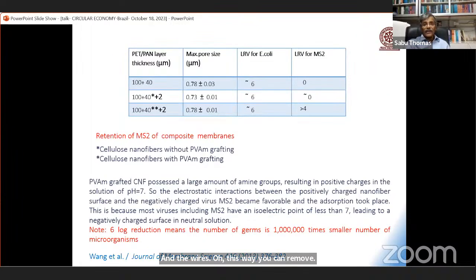And you see the logarithmic reduction value for bacteria is 6. The logarithmic reduction value for a virus could be greater than 4. So you can have a very good removal of viruses. And you see the pore size of the membrane, something like 0.78. Okay, that's the pore size of the membrane. Quite small, so that you can remove them.